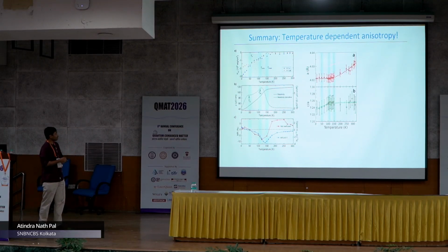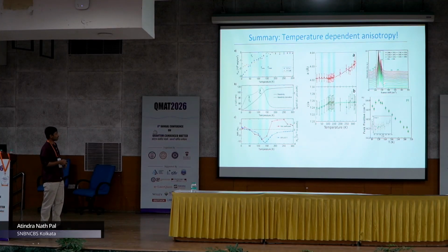And actually I have not shown the XRD measurement. XRD measurement could not detect any kind of structural transition. There is no detectable structural transition. So that is why we did Raman spectroscopy, and Raman spectroscopy shows that near the spin reorientation transition, spin and lattice strongly couple, and it can soften the phonons.